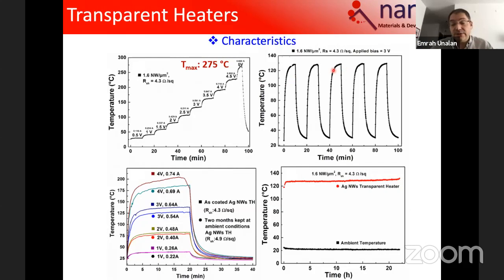And these devices are highly reproducible. These are on-offs for 5 cycles, which doesn't really give any change in characteristics. And even if you don't coat the surface, as you see, if you keep the device on bench top for 2 months in ambient conditions, the characteristics do change a bit. But as I said earlier, we have some protection methods that we can apply onto these heaters.